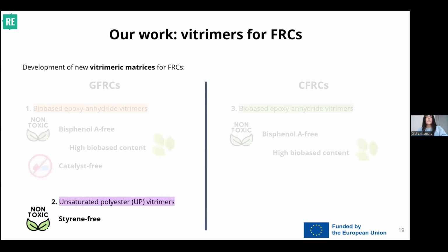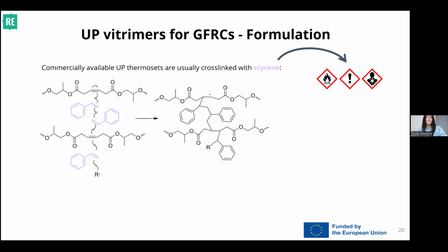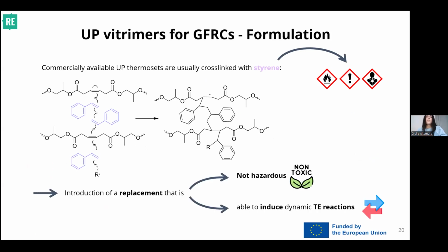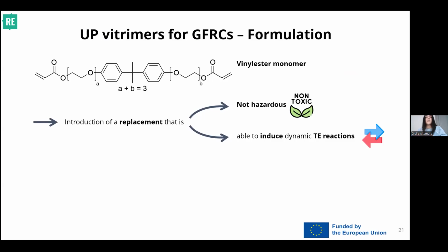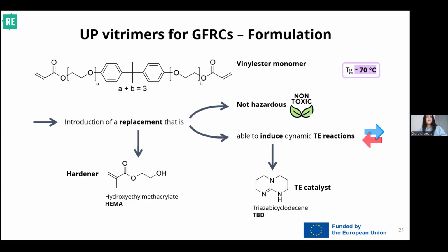Now, coming to the last material, unsaturated polyester. Let's say that in general, the main problem at commercial level of unsaturated polyesters is that they are usually cross-linked with styrene, which is very good at cross-linking, of course, but it's not the safest chemical on the market. Therefore, our purpose was to introduce a replacement to it that was both not hazardous, but that was also able to induce transesterification reactions within the network, creating a vitrimer. Therefore, we started by using a vinyl ester monomer as a base that contained esters, but not hydroxyl groups. And we added, instead of styrene, hydroxyethyl methacrylate, HEMA, which not only was able to cross-link the vitrimer, but also introduce some hydroxyls.